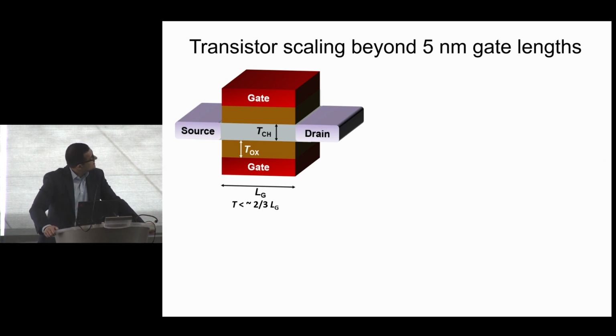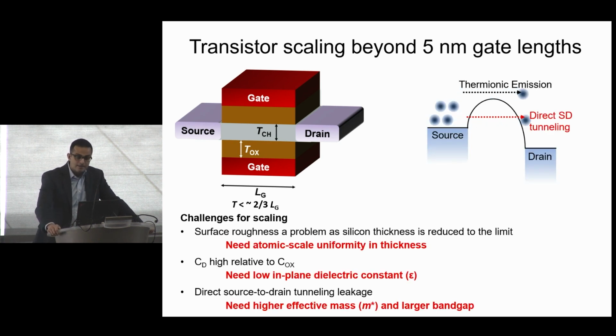Now, if I start by looking at the nanosheet transistor structure, just looking at one layer, so you have a dual gate, top and bottom, and if I start to look at this device scaling beyond 5 nanometer gate lengths, then a number of problems arise. And one, of course, is that the electrostatics of this system starts to suffer. The drain capacitance starts to compete heavily with the gate capacitance. But also, direct source to drain tunneling becomes a major problem. And this is carriers directly tunneling through the barrier.